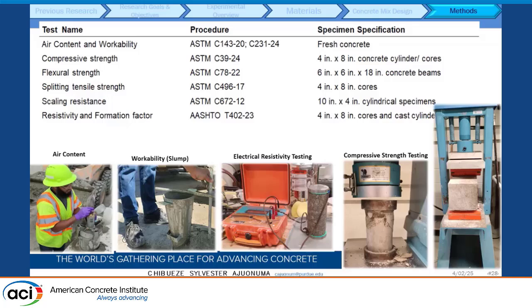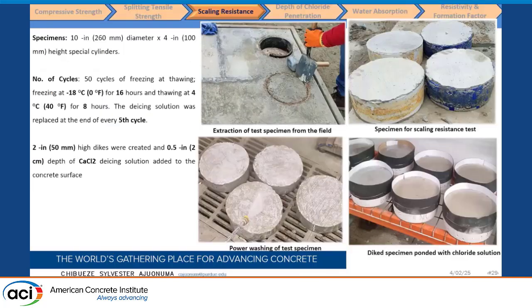For the splitting tensile strength, we extracted cores from the slabs in the field, and they were tested. For scaling resistance, we also had some cylinders extracted and tested, as well as the resistivity and formation factor. If you noticed during the formwork, we improvised and created special 10-inch by 4-inch cylinders, which we extracted.